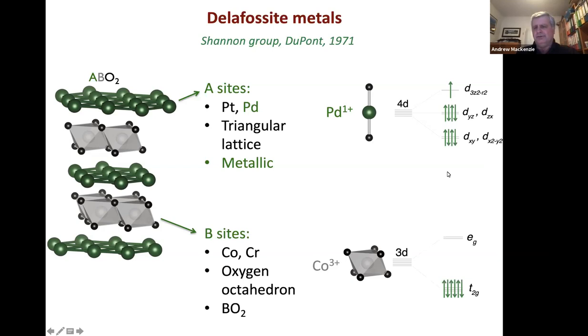If we go to the transition metal oxygen octahedra, the transition metal is always sitting in the 3+ valence. And if it's cobalt, that is cobalt in the 3d6 configuration. And it sits in the low spin state. So all the t2g's are occupied. There's a big gap up to the eg's, which are unoccupied. And the material is entirely non-magnetic. There's no moment associated with the cobalt. It turns out that the cobalt oxide bands with this configuration of cobalt are insulating, that there is a Hubbard U plays a role in determining the electronic structure, but they would have been band insulating anyway.